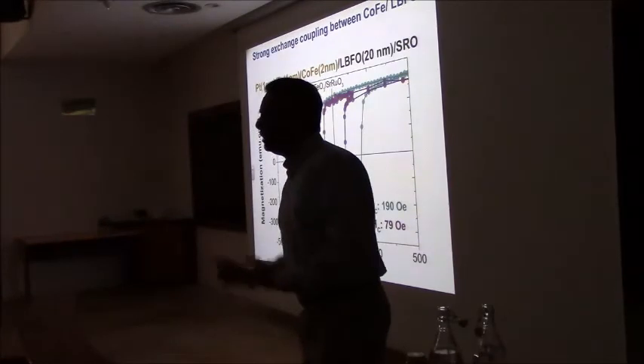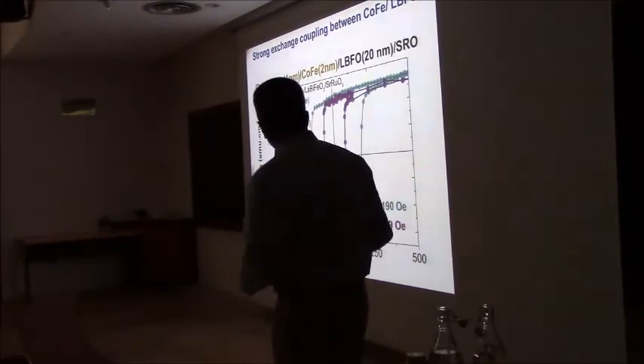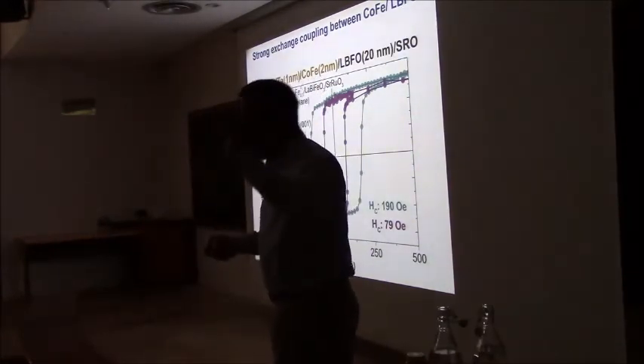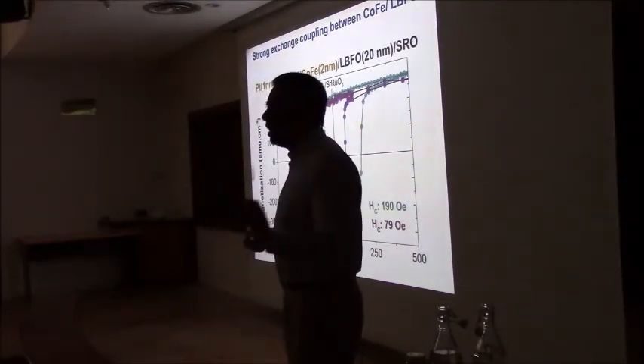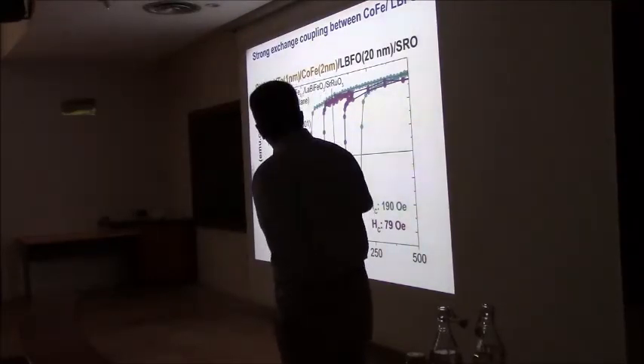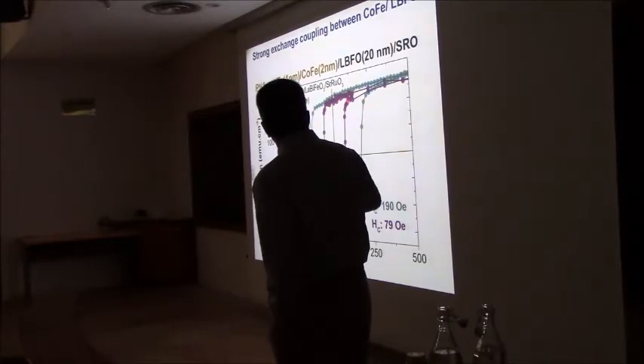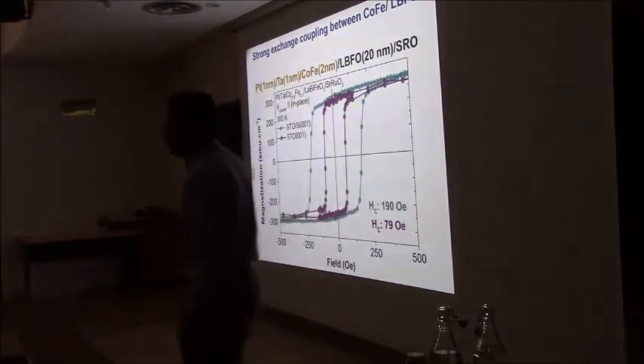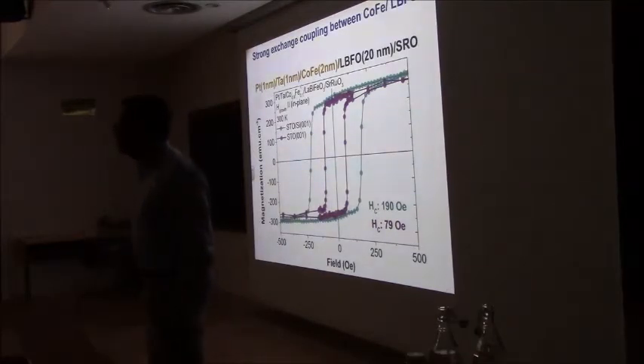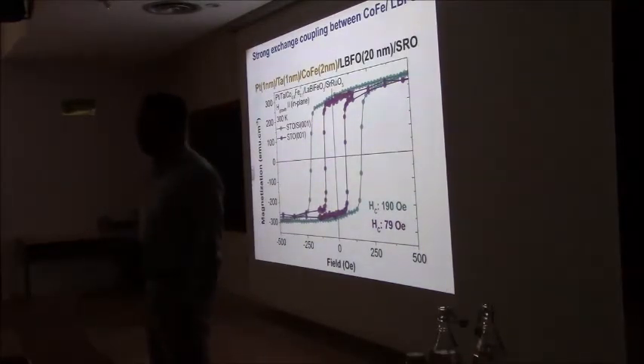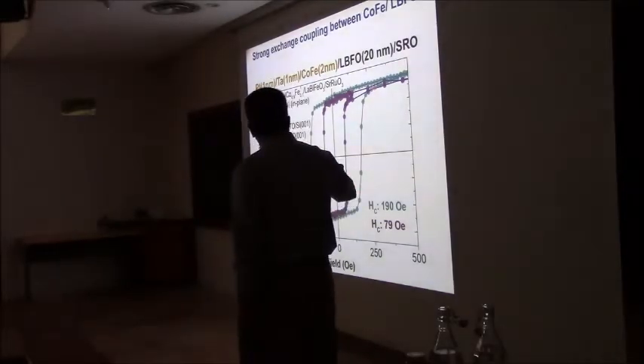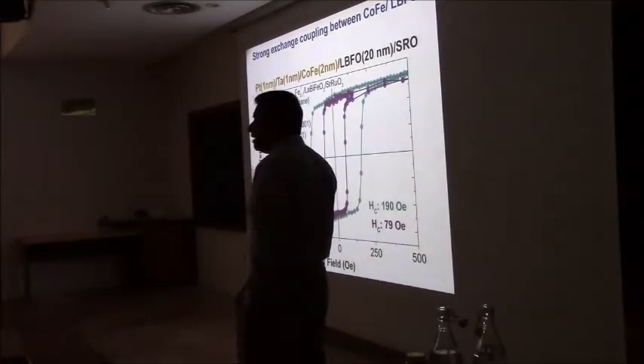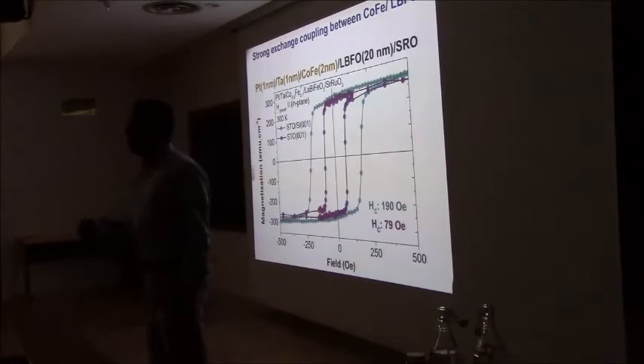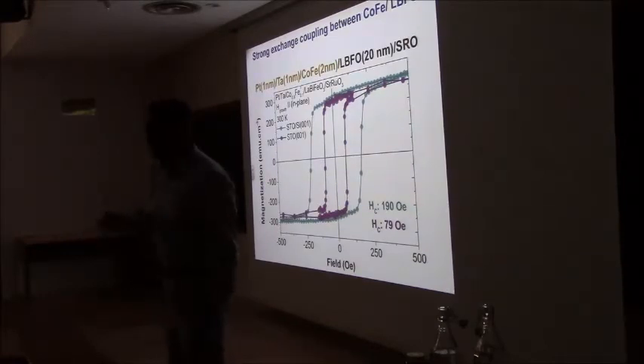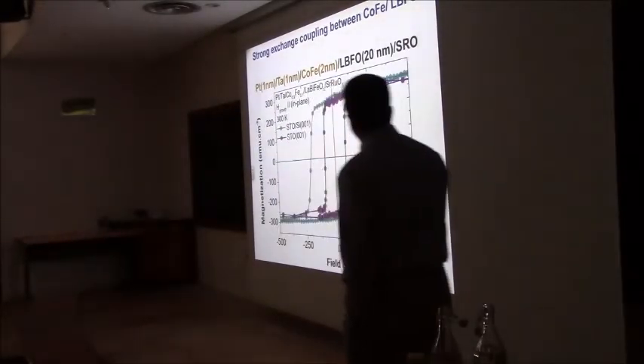The last piece of it, and this is where we are, we don't know beyond this point, is the fact that at 20 nanometers with lanthanum doping, very strong coupling still to a ferromagnet. This is the ferromagnet on strontium titanate substrate. On silicon, we see even stronger coupling. We think that's purely because the domain structure on silicon is very different than on these oxide substrates. This is something that needs to be understood because at the end of the day, most of these devices are going to be made on silicon. So we need to be worrying about what happens in the domain structure.